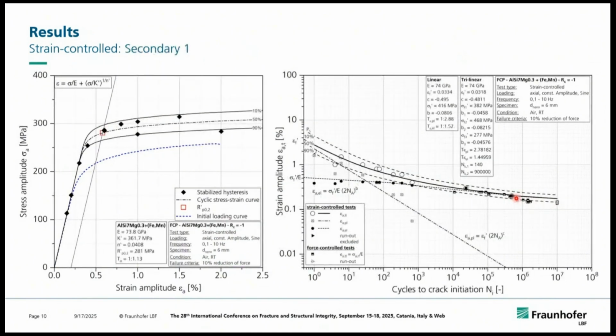When we go over to secondary 1, we see on the strain life curve something like a flattening, and I'll show you in 2 slides the comparison between those curves. Overall, we see, especially in the low cycle fatigue regime, some flattening. This comes from the reduction of the elongation at break, for sure, that we could see in the quasi-static data. And on the other side, a bit of an increase in the elastoplastic regime when it comes to the scatter band of the stress strain curve and also the strain life curve.